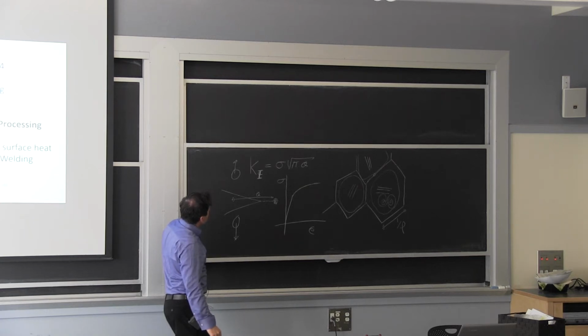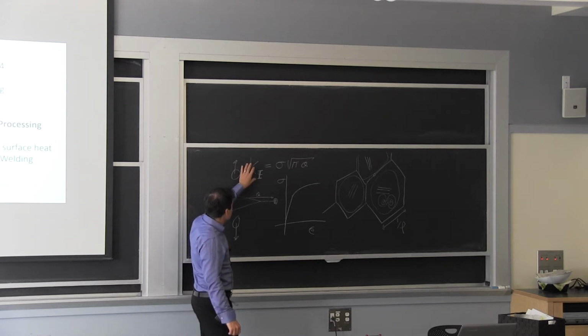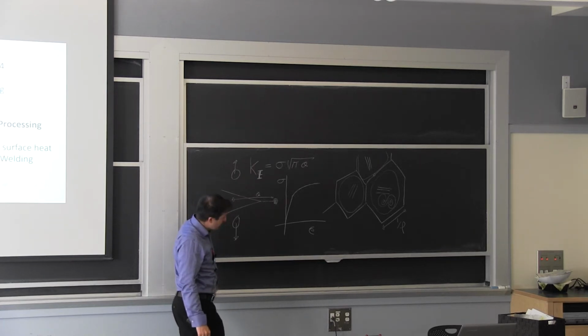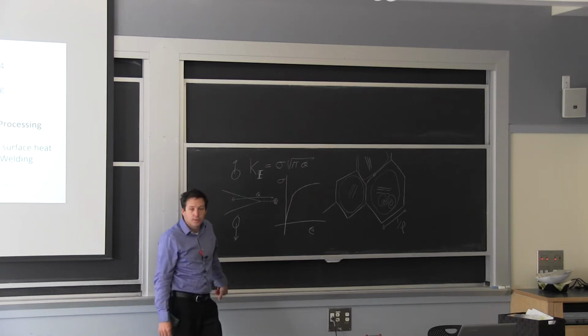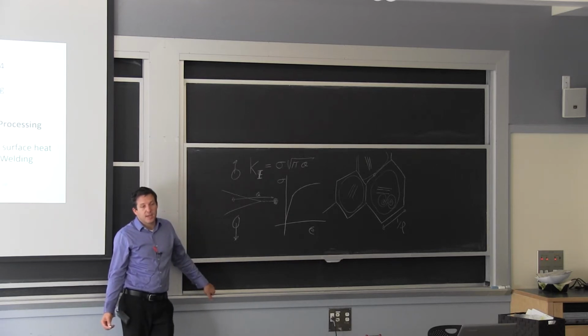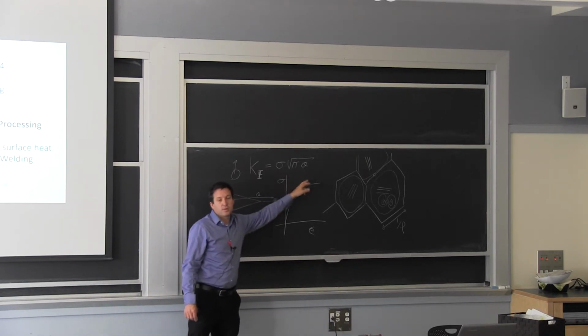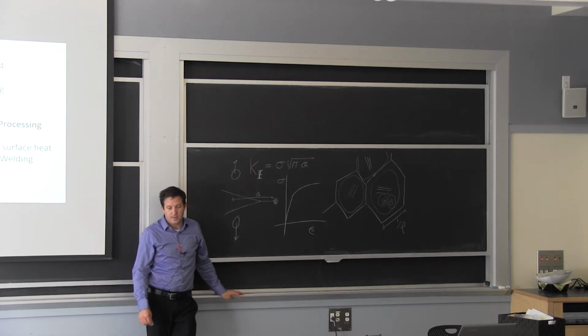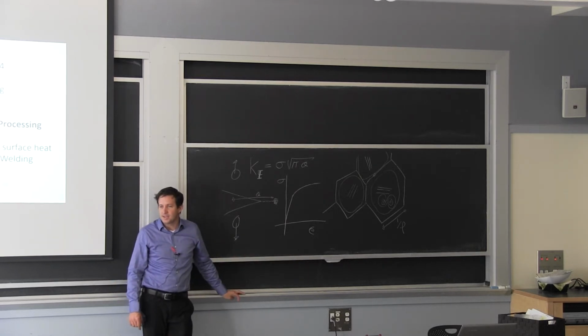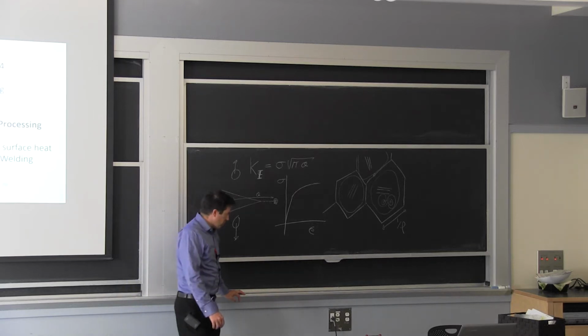So if you have a material that has very, very low fracture toughness, it's going to start breaking when the stress intensity is fairly low, something of the order of 15 ksi square root of inch or something like that. If it's a very mild steel, you're looking at a number that's more towards 200. So with that respect, given that we have a square root factor here, if we have a range of 20, it's a range of 400 in the capacity to resist cracking. So it's a very, very large difference between a ceramic and a piece of metal. And therefore, we use fracture toughness.